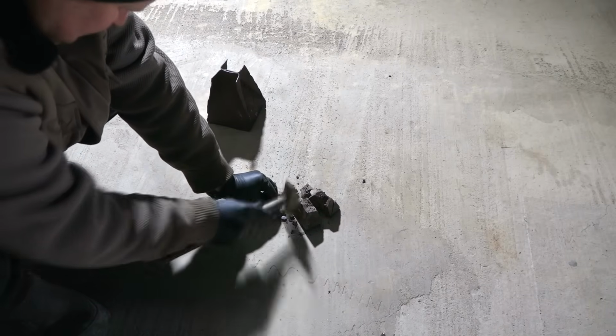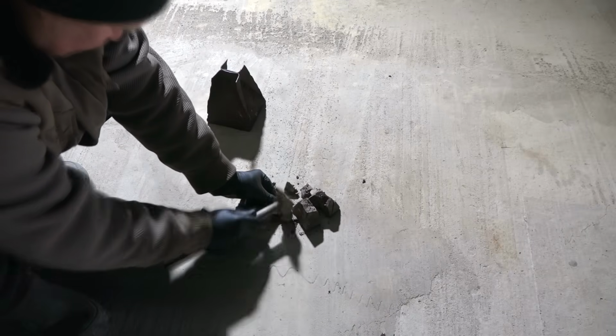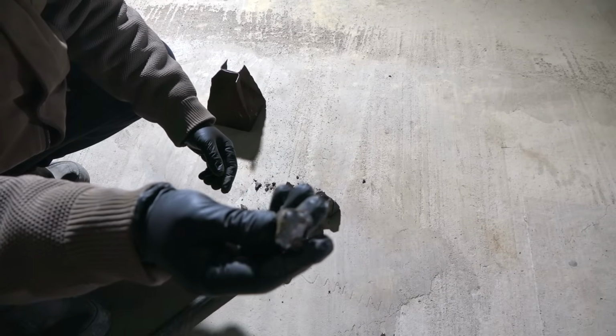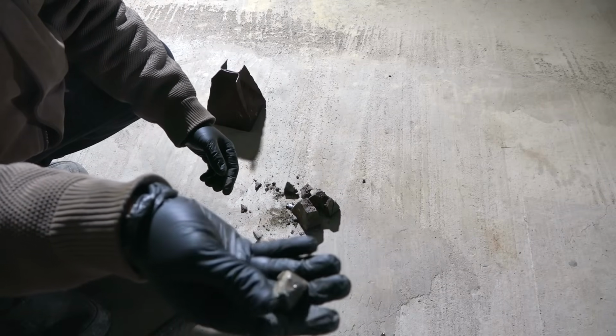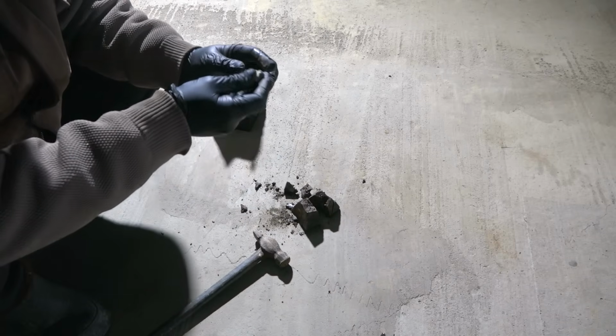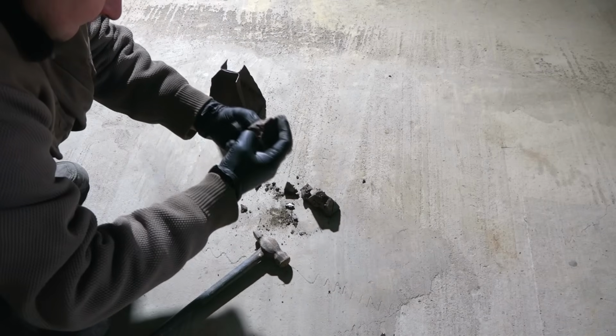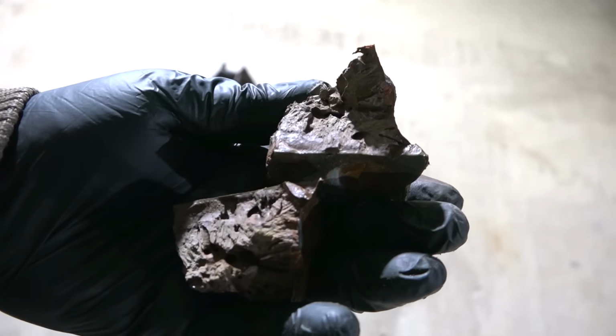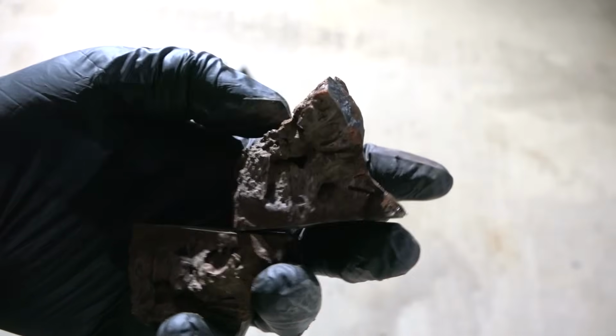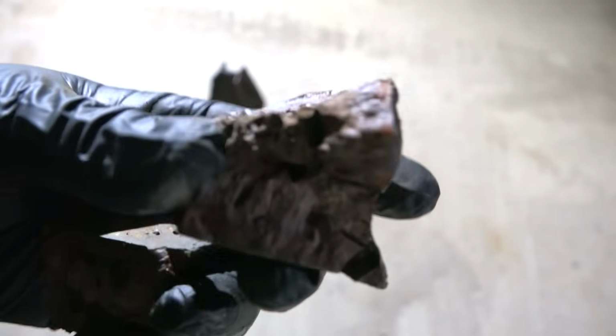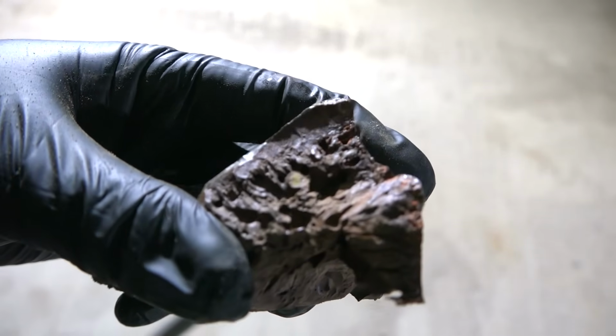But if I used chemistry to extract all the gold from the concentrates, it would take me several days. It would be a waste of time. And it took me 2 hours for this procedure, and it will take the same amount of time for the cupellation. This time the slag has a characteristic brown color. The alloy turned out to be brittle and vitreous, which means everything is fine.